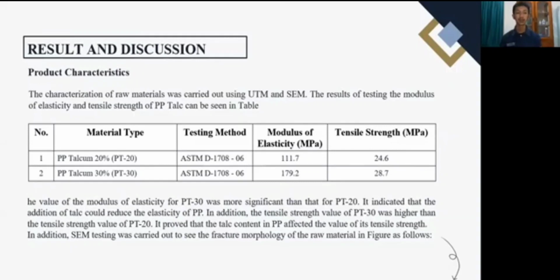The value of the modulus of elasticity for PT-30 was more significant than that for PT20. It indicated that the addition of talc could reduce the elasticity of PP. In addition, the tensile strength value of PT-30 was higher than that of PT20. It proved that the talc content in PP affected the value of its tensile strength. In addition, SEM testing was carried out to see the fracture morphology of the raw material in the picture as follows.